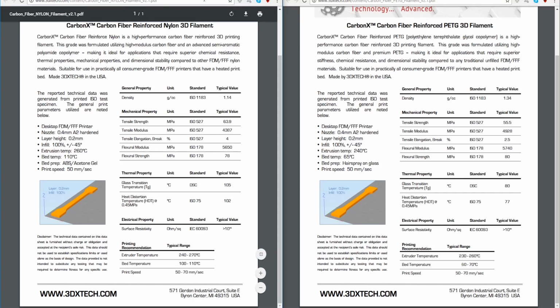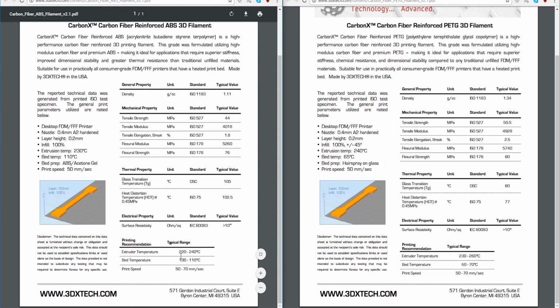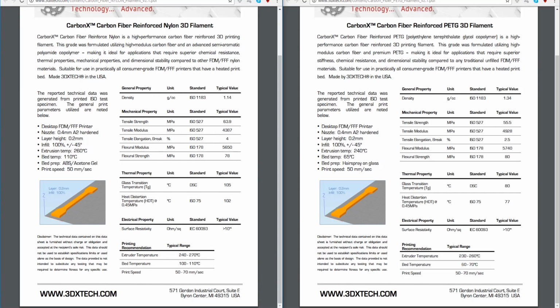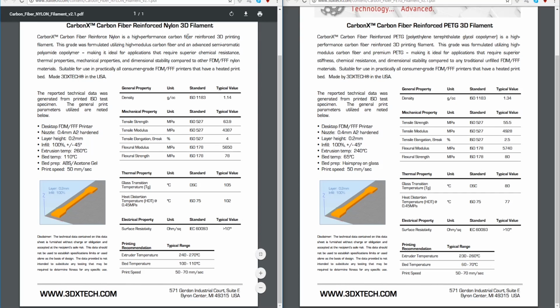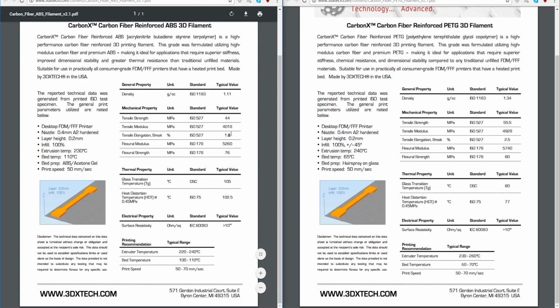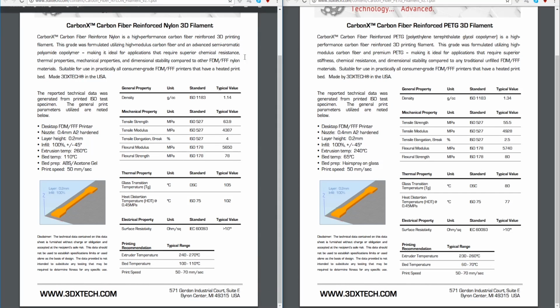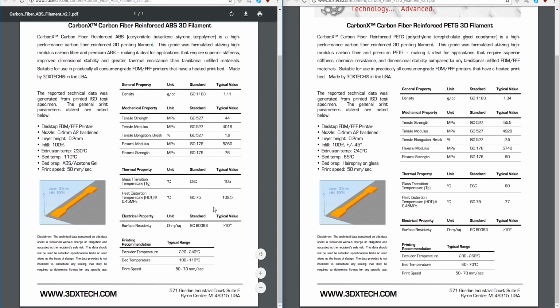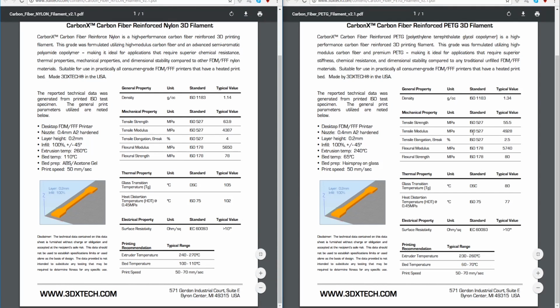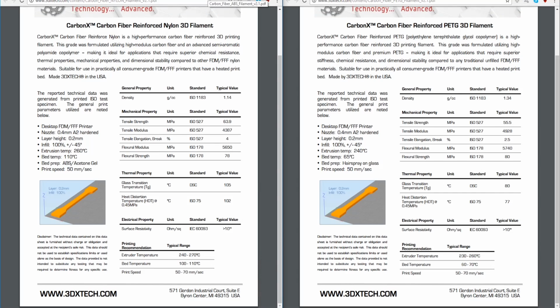Yeah, ABS. Well, here ABS, I mean, if you could print the higher temperature, go with nylon. Nylon beats ABS hands down, easy. ABS just kind of loses what it's good for, which is its flex, and its tensile, and its temperature stability is pretty good. But if I were to pick between ABS and the nylon, the nylon's got way better properties. So for ABS, I don't know. I would pick ABS if I couldn't hit 260C. If I couldn't hit 260C, I would use the ABS. But other than that, I would use the nylon. So, use the ABS if you can't print the nylon.